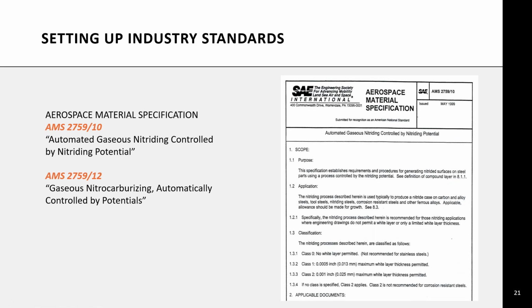Thank you. So here, out of this research, which is really our core competence, have come two main specifications, which are today industry standards. One is 2759-10, which is automated gas nitriding controlled by nitriding potential, which is one step after the 2759-6, which was describing control by dissociation. And then you have 2759-12, which talks about gas nitrocarburizing, automatically controlled by potentials. It's not a typo. In this case, we have two potentials. One is nitriding potential, and the second one is the carburizing potential. So you have a Kn and a Kc that are being controlled together in order to achieve the right white layer composition in terms of gamma prime and epsilon. Next, please.